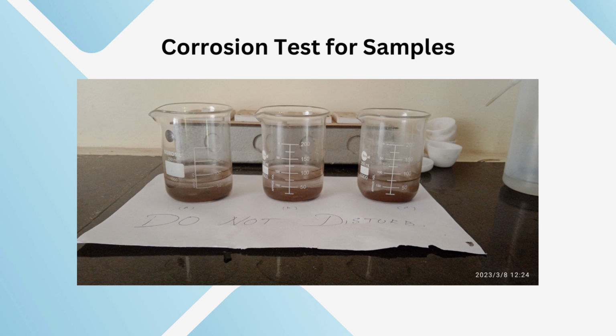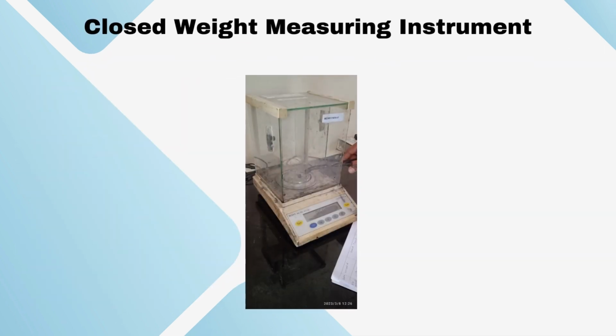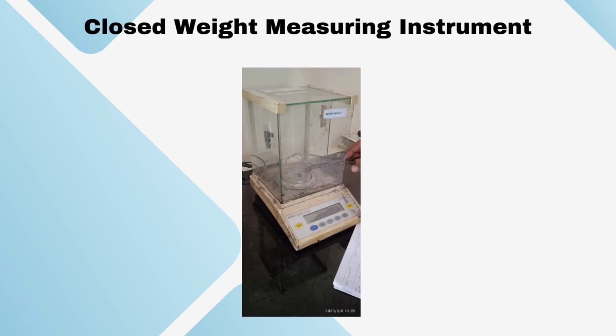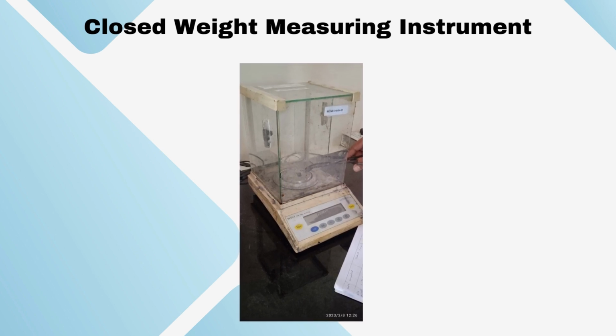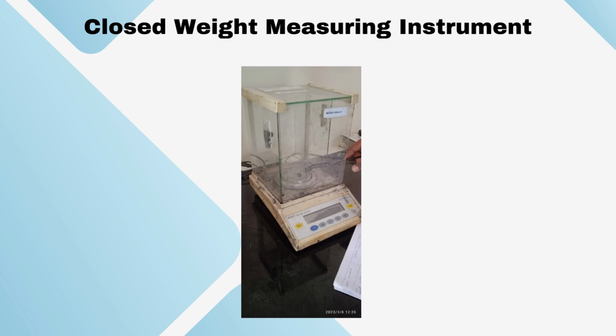the metals. These samples of aluminum, silicon, and magnesium alloy were cut into pieces and they were then abraded using a variety of emery papers of varying abrasiveness. All three samples were cleaned with distilled water before being cleaned and dried with acetone. The samples were weighed initially, and the initial weight of all three samples, uncoated, coated sample 1 and coated sample 2, was noted before immersing them into acid for corrosion testing.